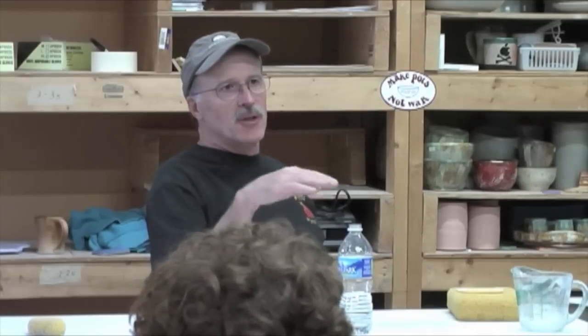Raku kilns are the blunt instrument of pottery firing. They are not as fine an instrument as a high fire kiln, when you're trying to get that last cone to drop and you're fiddling with your dampers one way or the other. Usually you have a burner that's way bigger than your kiln needs on a Raku kiln, so you can easily do one or the other. But after you get up to about 1,000 degrees, you should be able to dial it into neutral. And neutral is, at nighttime, you can see one little ghost flick of flame come off that exit flue of the kiln every now and then, and you know you're about as close to the most efficient use of gas and oxygen as you're going to get.